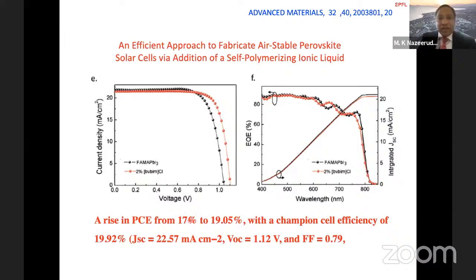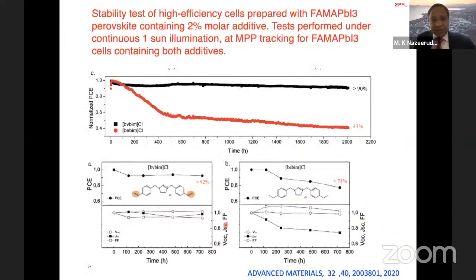By adding this ionic liquid, a small additive, 2% of ionic liquid, the efficiency increases from 17% to 19%. So this is an enhancement in the power conversion efficiency by using this ionic liquid. But the beauty here is we made another ionic liquid, very similar, except you don't have the double bonds.